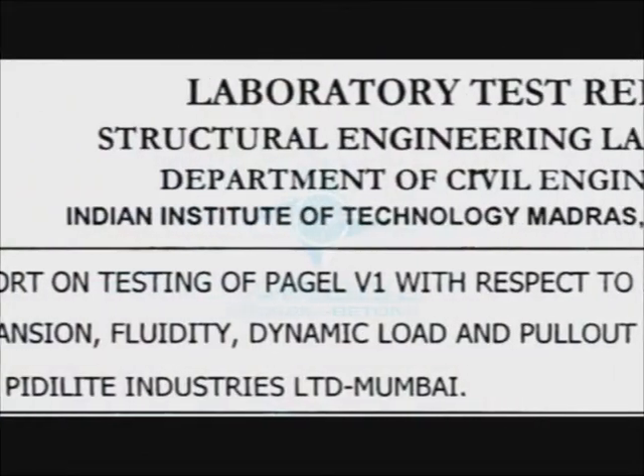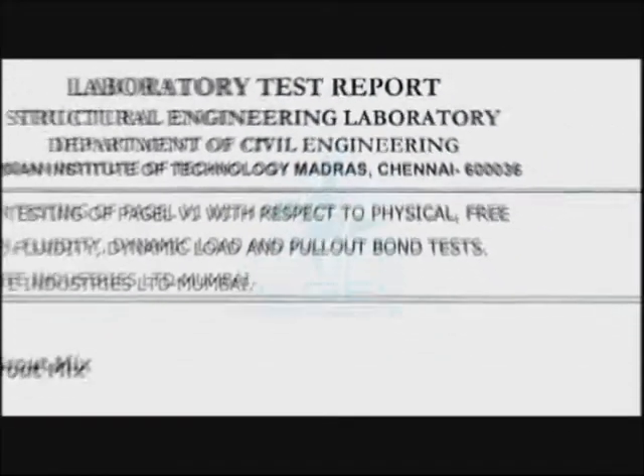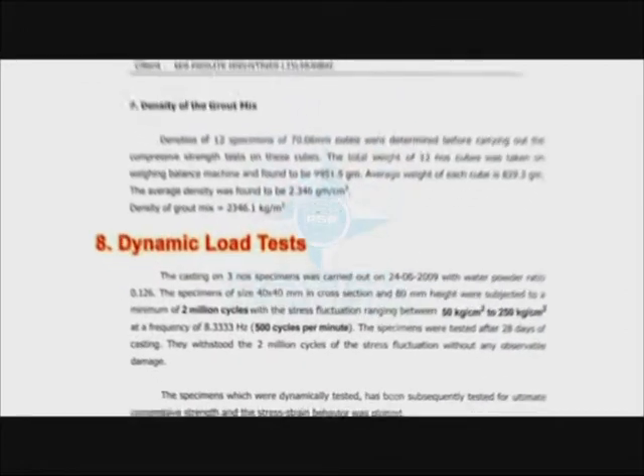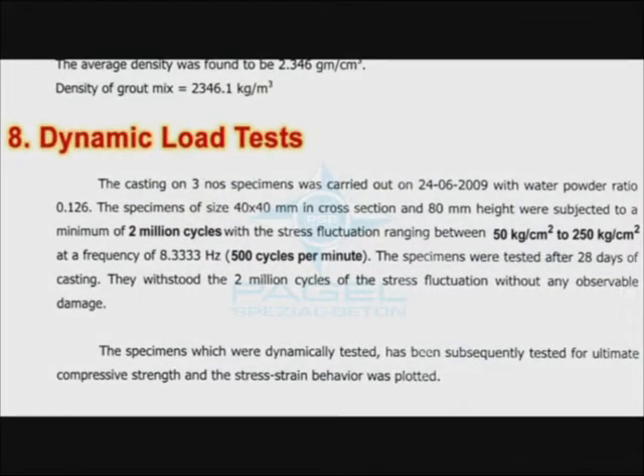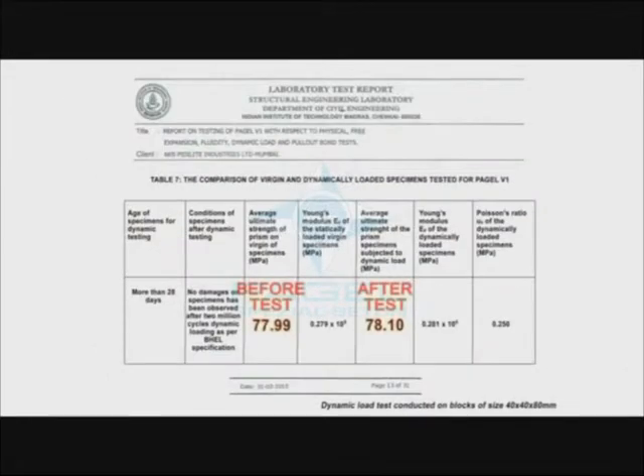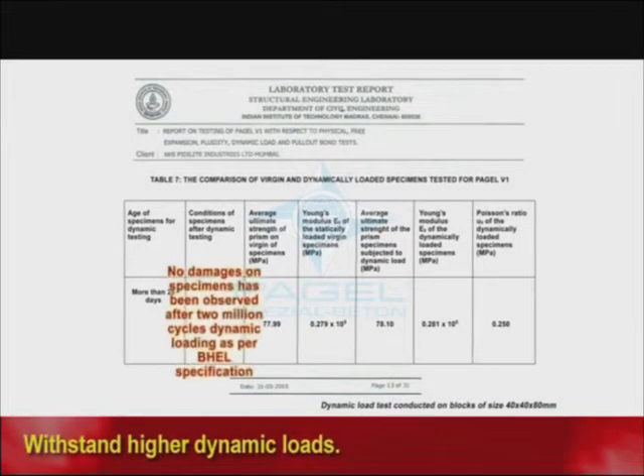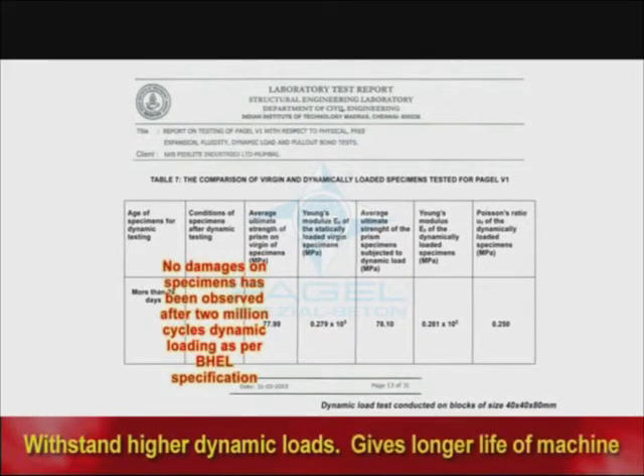The test report from IIT Chennai bears testimony to the superior dynamic load resistance of Pagel V1 grout. Even after 2 million cycles of load variation, the residual strength of Pagel V1 grout does not drop. Therefore, with Pagel V1, your structure will withstand higher dynamic loads, giving longer life of the machine.